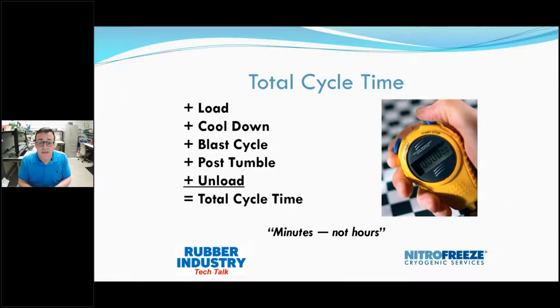Then we have the blast cycle. So this is when the basket is rotating in the machine and being blasted with media. That can range from a couple minutes up to, say, 10, 15 minutes. And if you're using a cryogenic tumbling process, it can be even longer, depending on your batch size and that. Then you have the post-tumble.